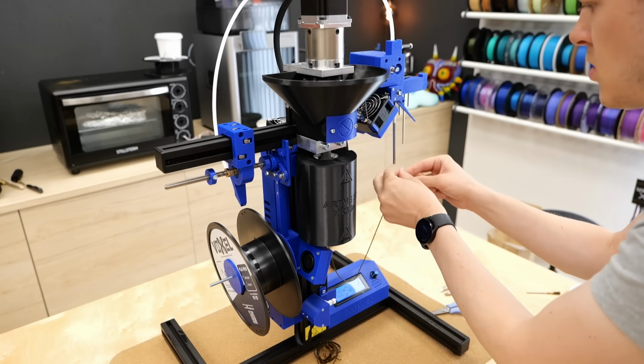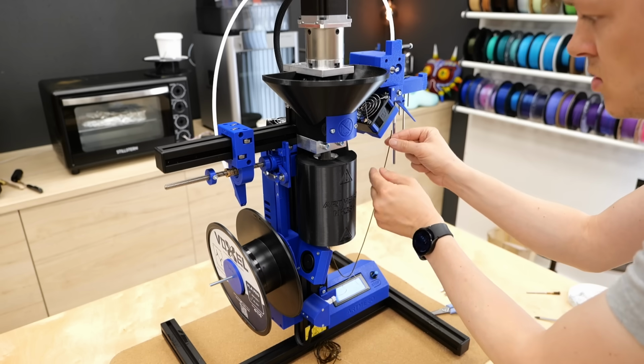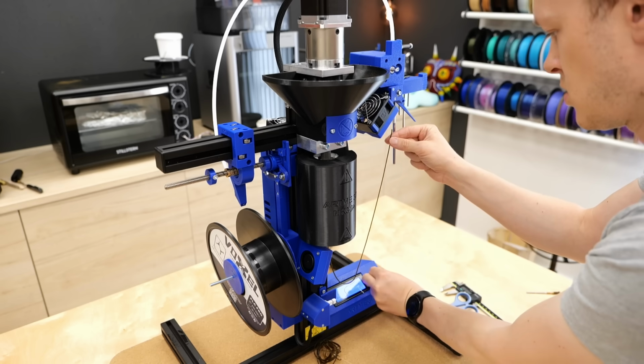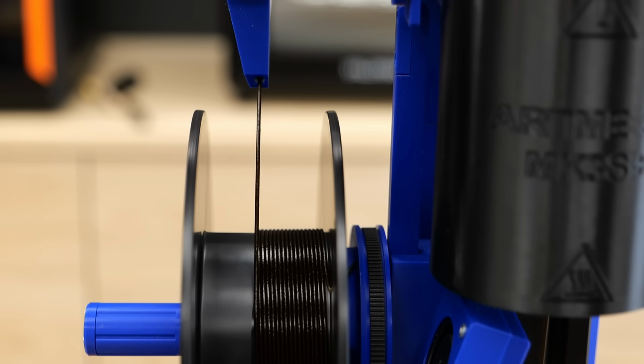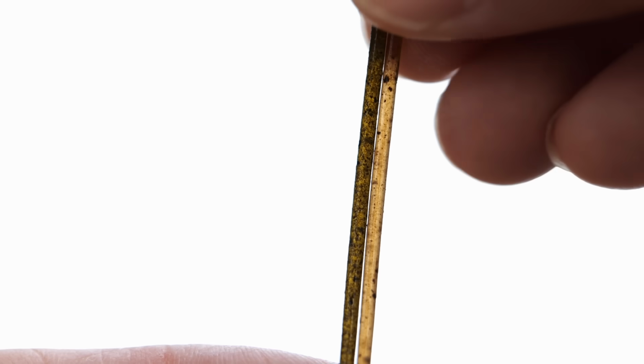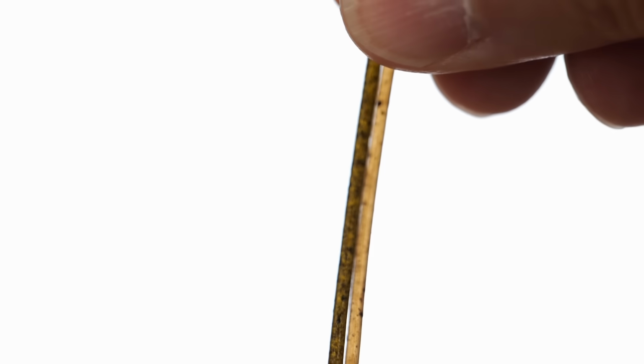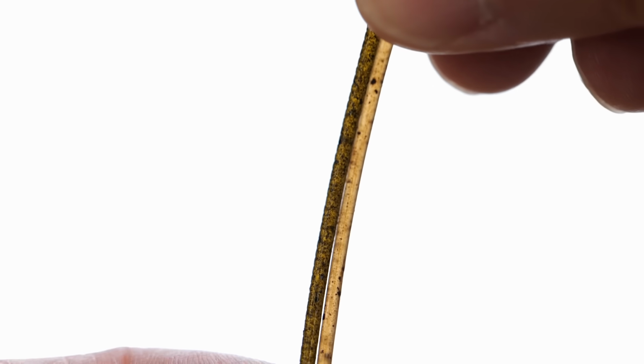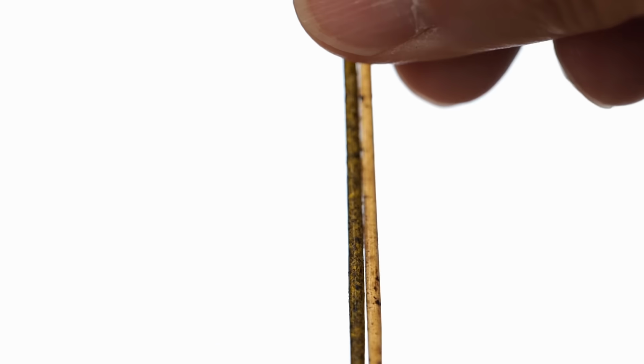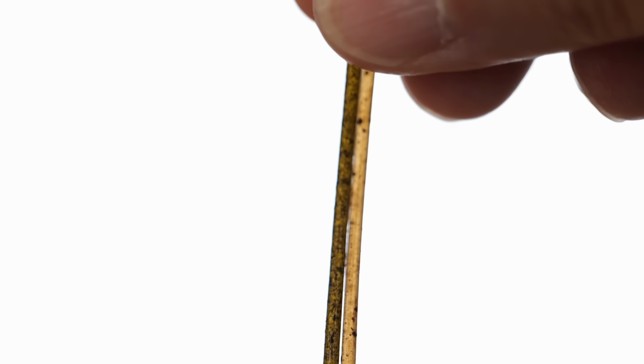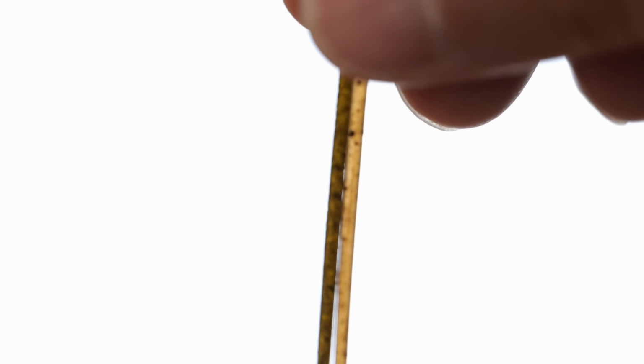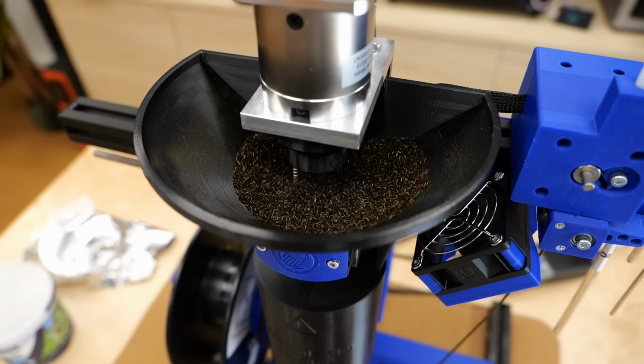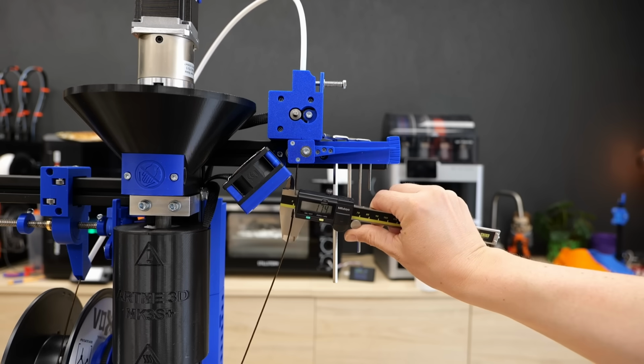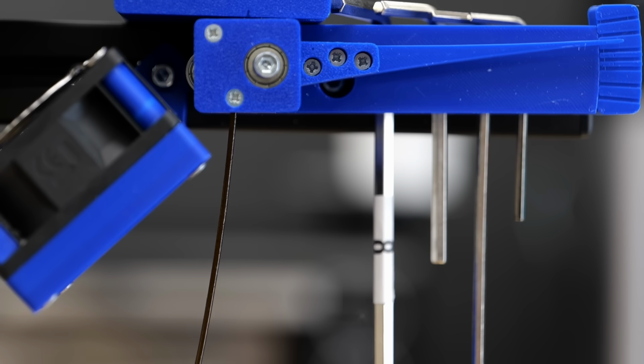Once everything came out of the nozzle evenly, it was time for spooling and the filament already felt way better. I was easily able to start spooling and the filament wound up really nicely. The other thing that was interesting to see was that even though it was the same material, the color became darker. I can imagine that this was due to the caramelization of the sugars that were still left in the cow poop. My pelletized material fed great, and also the diameter came out almost perfectly. I got a good amount of filament onto the spool and thought that I had finally tackled the problem when it snapped again.